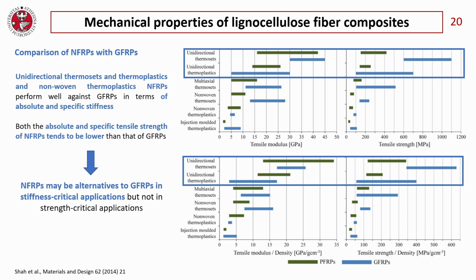In this chart, if we compare unidirectional thermosets and unidirectional thermoplastics reinforced with glass fiber and natural fiber, it is immediately clear that if we compare moduli, specific moduli and absolute moduli, we have a good comparison, okay? They are similar, they have similar stiffness. If we compare instead the tensile strength, the glass fiber performs better with respect to natural fiber. The conclusion is that the natural fiber can be an alternative to glass fiber reinforced polymer only in stiffness critical applications, but not in strength critical applications.